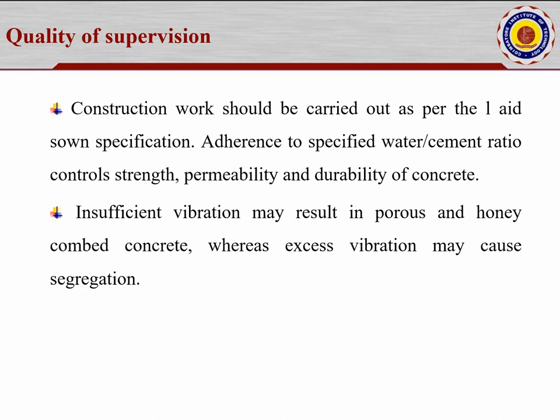Quality of supervision is an important factor. Construction work should be carried out as per specifications: the specified water-cement ratio controls strength, permeability, and durability of concrete. Insufficient vibration may result in a porous and honeycombed structure, whereas excess vibration may cause segregation. In site concreting, if vibration is not done properly, honeycombing occurs — as can be observed in the slump cone test when compaction is not done properly.